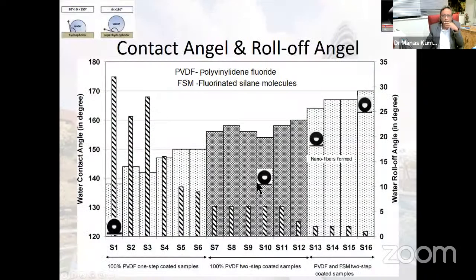So let's see this graph, I think it gives us a much better picture. This side is the contact angle. The less the water drop touches the surface, the greater the contact angle would be. The maximum contact angle possible is 180, theoretically. And this is the water roll-off angle, meaning if you put a water drop on the surface and incline the surface, at which angle the water starts to roll off. When we use the single layer coating, these are one-step coated samples, S1 to S6. You can see when we reduce the percentage of PVDF, this is for 1% and this is for 0.5%, they are almost the same. We have not found much benefit in terms of the contact angle.